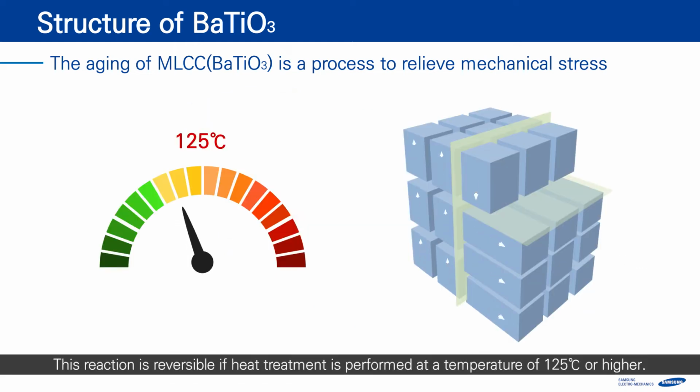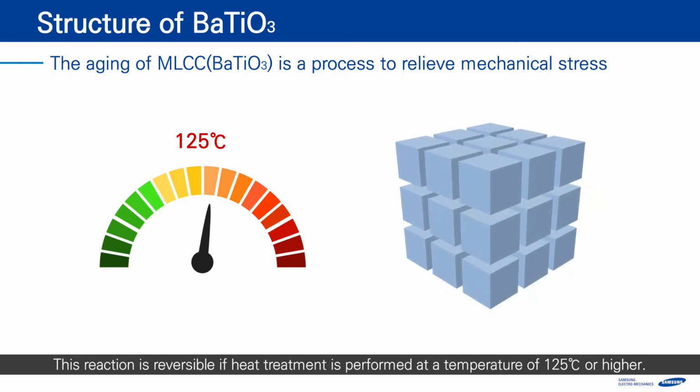This reaction is reversible if heat treatment is performed at a temperature of 125 degrees Celsius or higher. The lattice returns to a cubic structure without polarity, and capacitance is recovered.